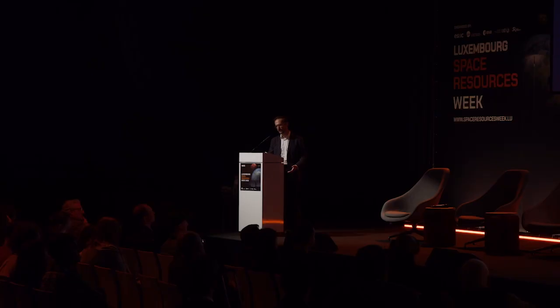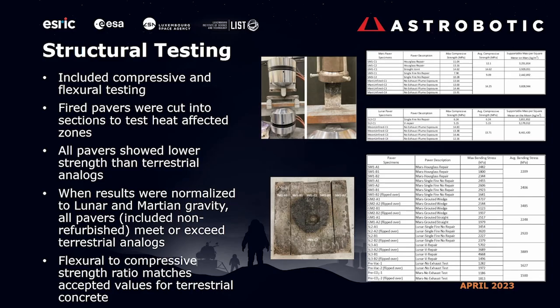And then after the fact, we really needed to know what was happening with the material. So we ended up cutting the pavers up into slices, both with areas that had been fired, areas that had experienced one landing, and areas that experienced multiple landings. And we did some structural testing on them, specifically compressive and flexural testing.